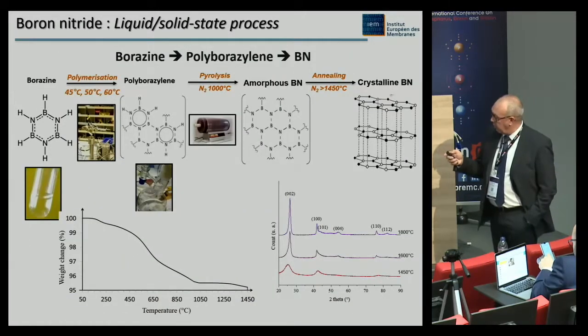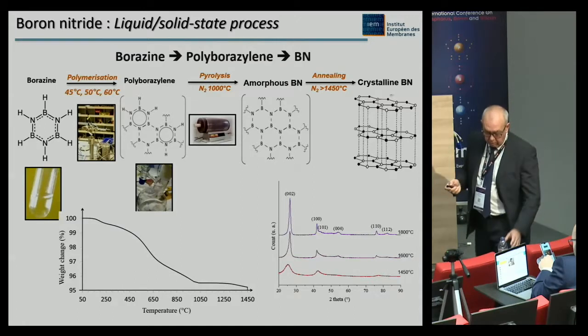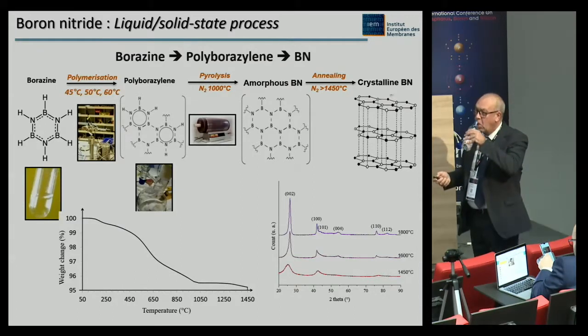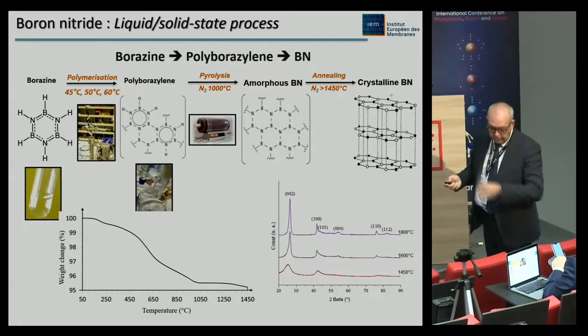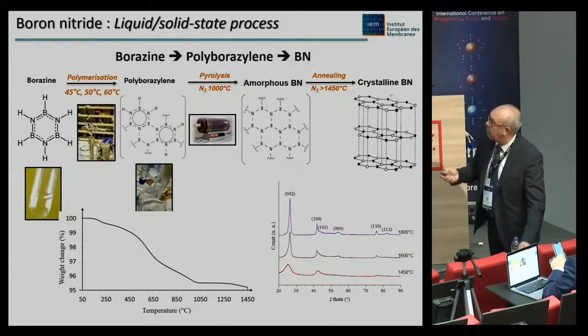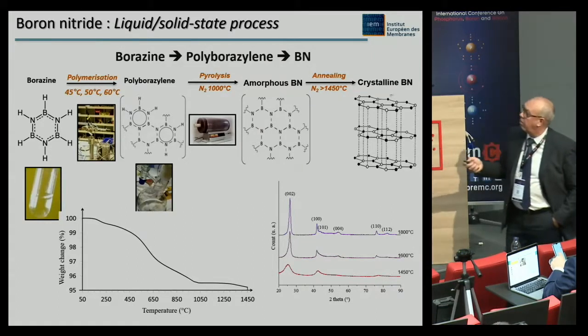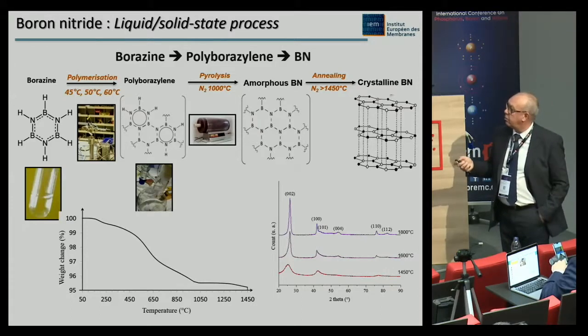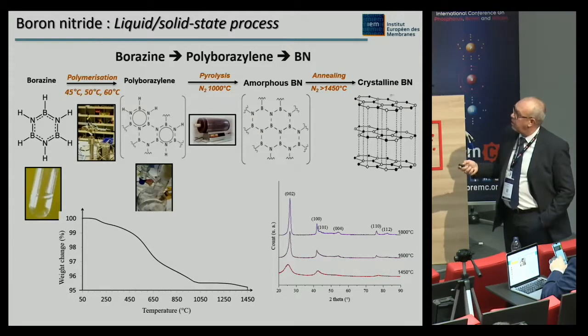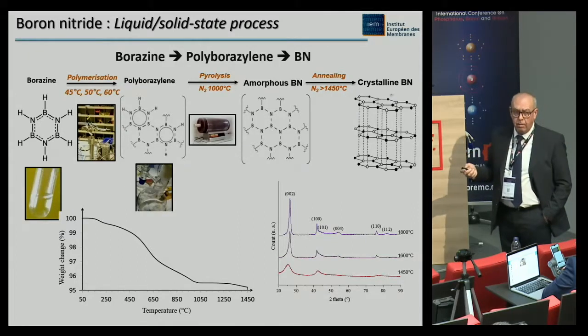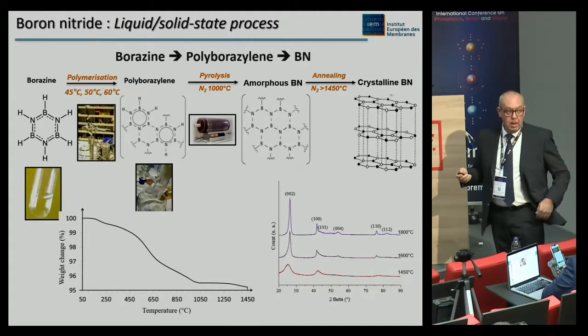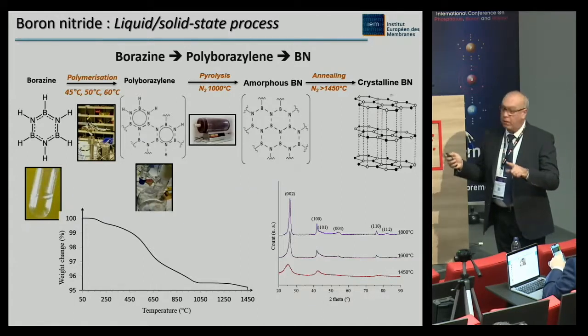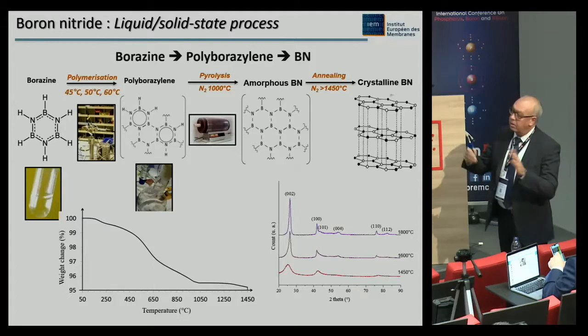So now if I change precursor, going to borazine, this precursor can be polymerized very easily at low temperature, from around 45, 50 or 60 degrees. This is a liquid. And you can obtain this polyborazylene with direct BN bond between the borazine rings, explaining the low processability of these polymers anyway, but this is another story.